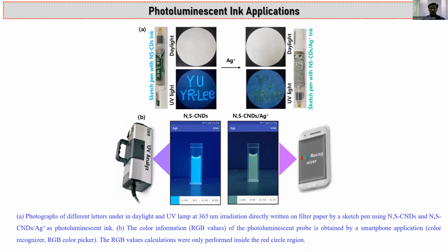Next we go to the further applications of these carbon dots. Previously I used this as photoluminescent ink. Here also I applied the bright blue and green color emission in a marker pen. Both aqueous solutions can be filled in a commercially available marker pen and directly used as a photoluminescent ink. Moreover, this photoluminescence is highly stable for at least 6 months under ambient conditions, or we can say at room temperature also.